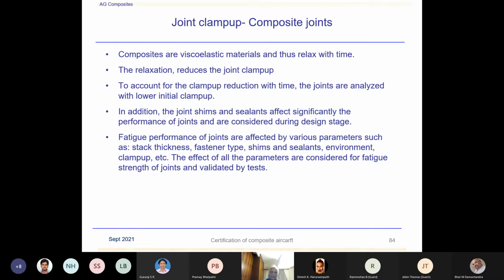That's what we found. Now, the question was regarding this one when I was showing a slide on the fatigue issue of the joint, whether it's due to the clamp up, and I did explain, yes, the clamp up, but however, the clamp up is taken into account. So when we are doing the static joint analysis, we consider the reduced clamp up, which is validated by the test data. We determine the bearing strength using the test with the reduced clamp up, usually around 50%, or if you decide to go a bit lower, probably lower. And then based on that, the bearing strength level is determined, and that's used in static.